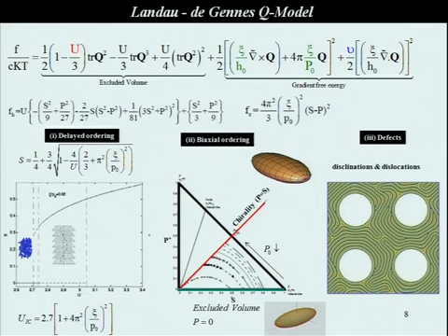So if you have a shorter pitch, you need to put more and more fibers to create a nematic phase from an isotropic phase. So this transition line, this is S as a function of nematic potential or concentration. These vertical lines are going to be shifted from left to right if the pitch decreases. Many systems are like this; for example, we know blue phases have very small pitch. So small pitch is also important.